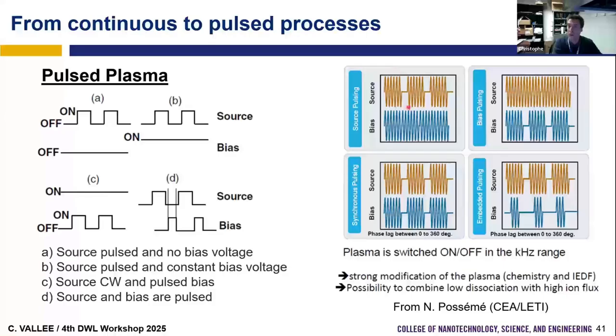So we have different ways of pulsing. For example, we can pulse only the source, or only the bias. We can pulse source and bias in synchronous pulsing, or we may have some lag in between. So it can be very complex, and it means that we may have a strong modification of the plasma. I mean, when I say the chemistry, it's because usually when we pulse, since we have a lot of off time, we have more molecular species and atomic species. So usually we observe a modification of the chemistry of the plasma, with more molecular ions or molecular radicals and atomic ions or atomic radicals. And we also modify the ion energy and its distribution.